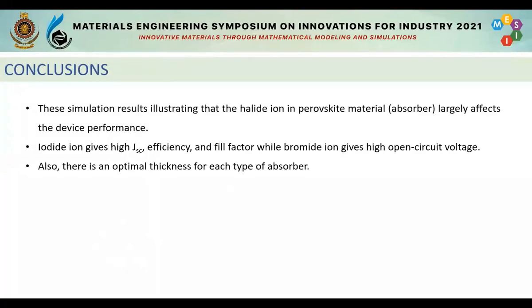In this research, we concluded that the halide ion in the perovskite material largely affects the device performance. Iodide ion gives higher short circuit current and fill factor, while bromide ion gives higher open circuit voltage. Also, there is an optimal thickness for each type of absorber.